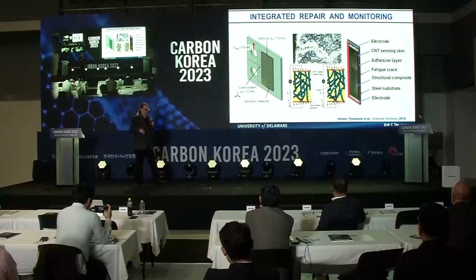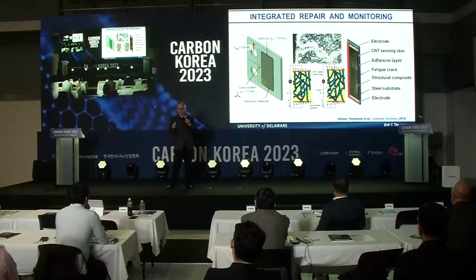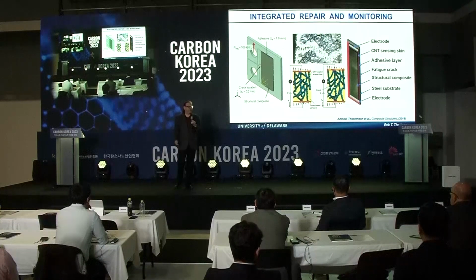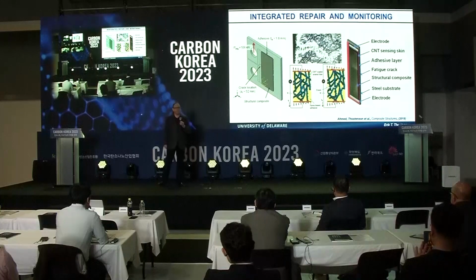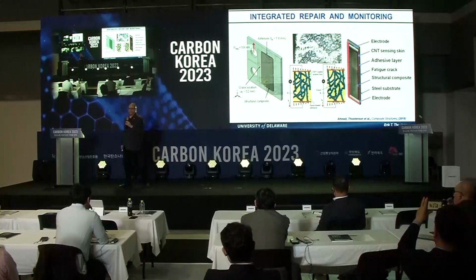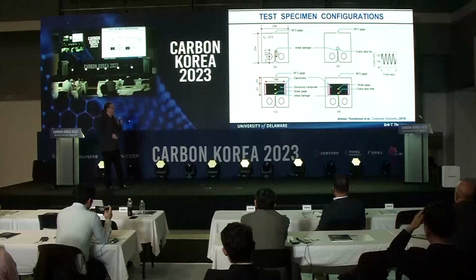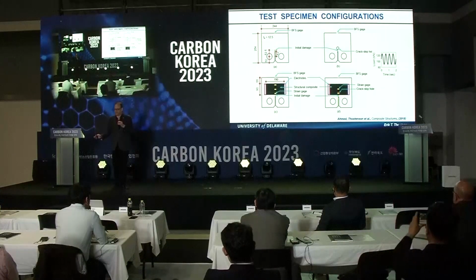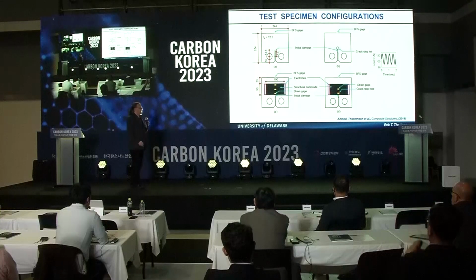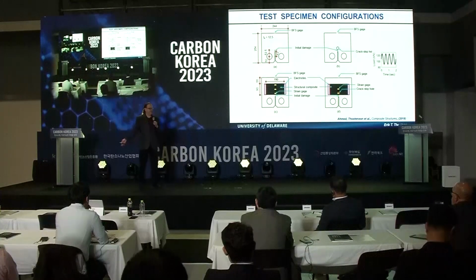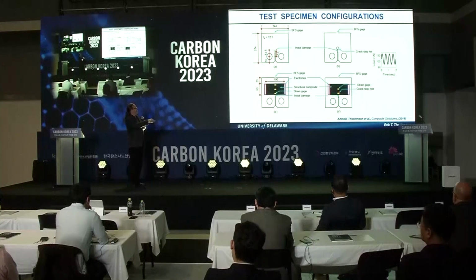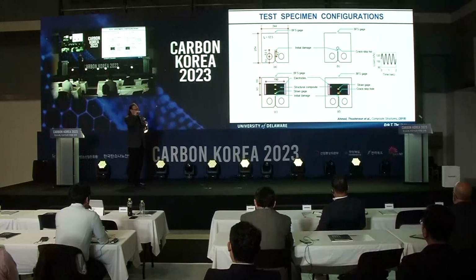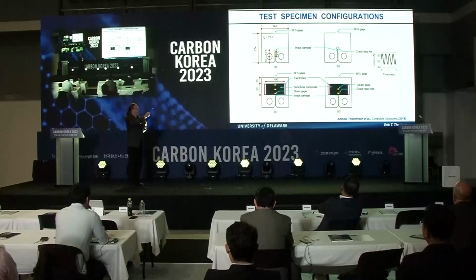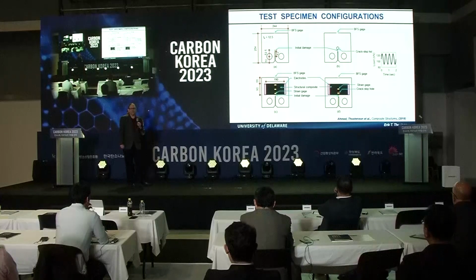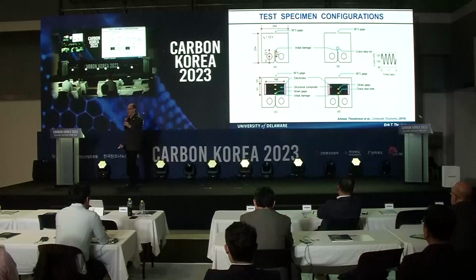So our idea, and we're talking to our civil engineering colleagues, they really like composites, but the critical barrier is that you're covering up the crack, so they can't inspect it anymore. So our idea was, well, hey, we have these cool sensors, let's see what we can do. This was funded by the Federal Highway Administration, a 5-year program. We took it from idea to actually putting it on a bridge. And what you see here are some of the specimen configurations that we tested in the lab: just the baseline where we drill a crack stop hole, but where we also apply a composite repair with and without a crack stop hole.